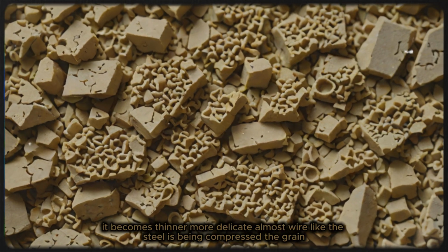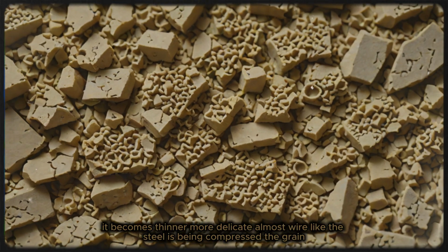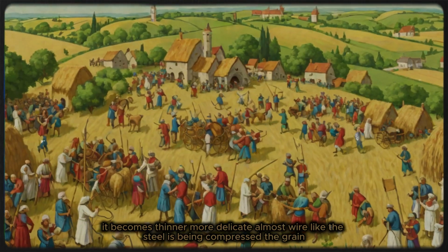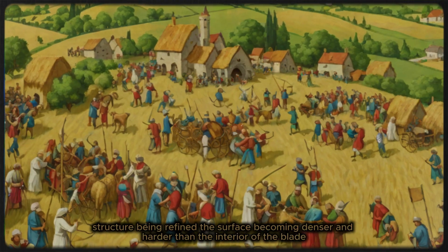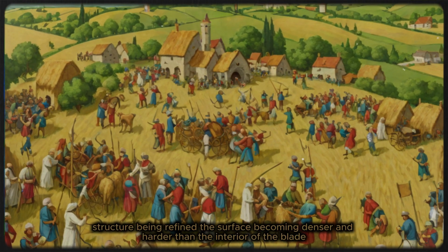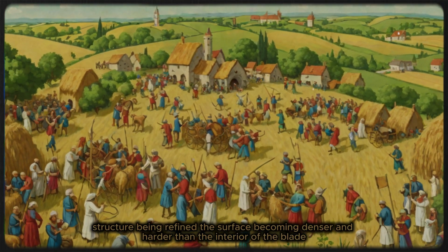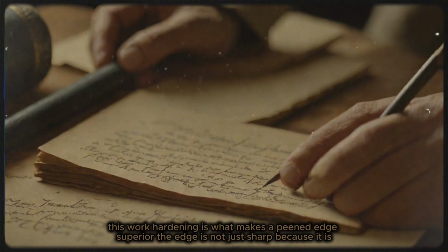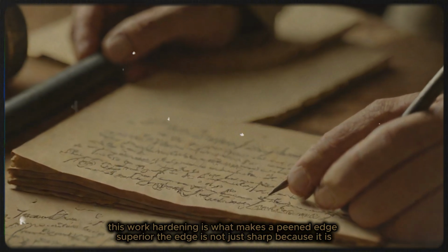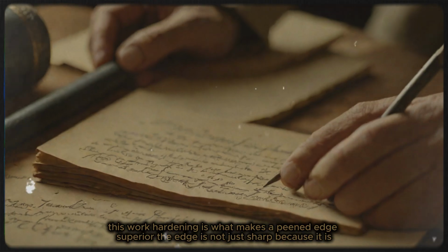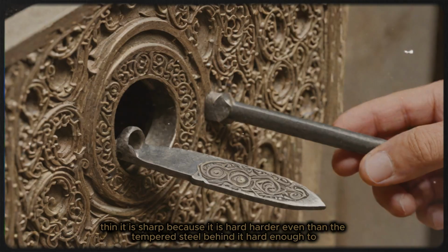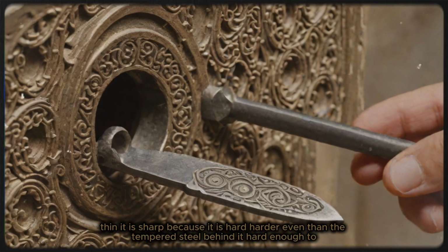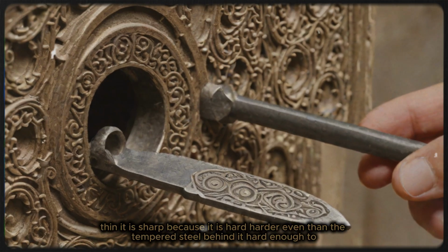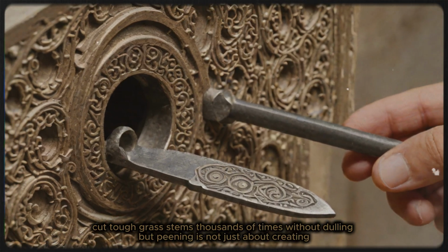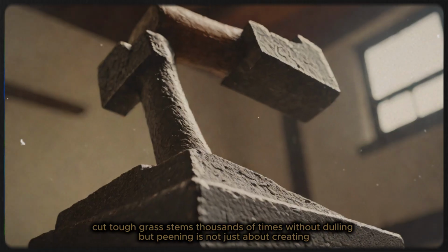It becomes thinner, more delicate, almost wire-like. The steel is being compressed, the grain structure being refined, the surface becoming denser and harder than the interior of the blade. This work hardening is what makes a peened edge superior. The edge is not just sharp because it is thin. It is sharp because it is hard, harder even than the tempered steel behind it, hard enough to cut tough grass stems thousands of times without dulling.